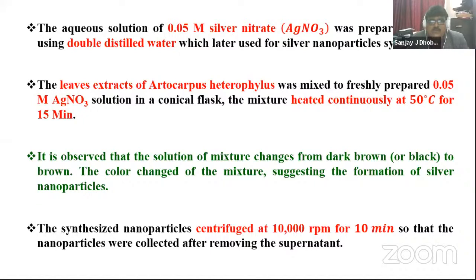A freshly prepared 0.05 molar silver nitrate solution is placed in a conical flask, and the mixture is heated continuously up to 50 degrees centigrade for 15 minutes. This temperature is very low, so some labs do not require a high temperature furnace, and people work with this method at a very low temperature. It is observed that the solution changes from dark brown to brown, and the color change suggests the formation of silver nanoparticles.